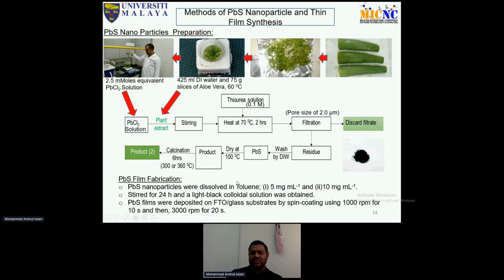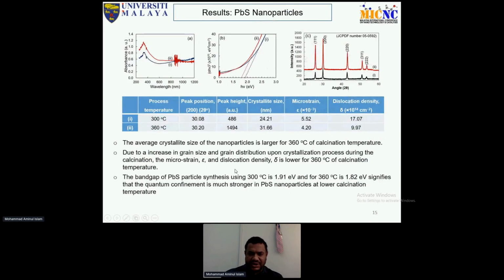Later on, because we want to fabricate the solar cell, we have to make it into a film. For this, the nanoparticles are dissolved in toluene with 2 different solution concentrations, and then we fabricate the film on top of an FTO glass substrate using spin coating, 1000 RPM for 10 seconds, and then 3000 RPM for 20 seconds. So here are some of our results.